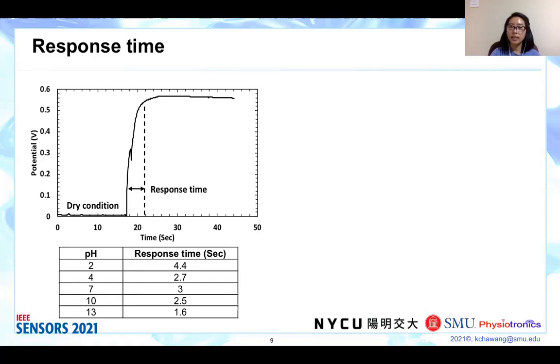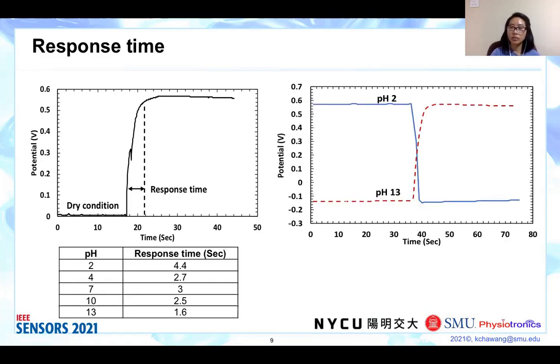The second type is when the electrode is switched between 2 extreme pH levels. The response time when switched from pH 2 to pH 13 is 3 seconds, and when switched from pH 13 to pH 2 is 4 seconds. In all the cases, response time is less than 4.5 seconds.